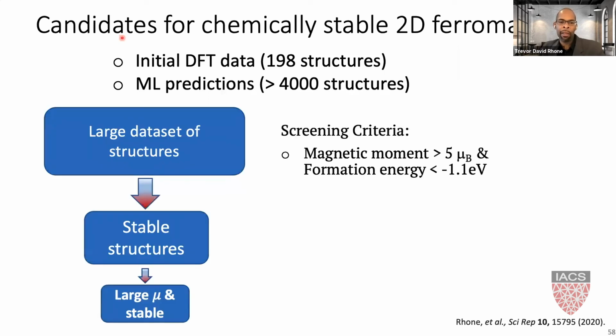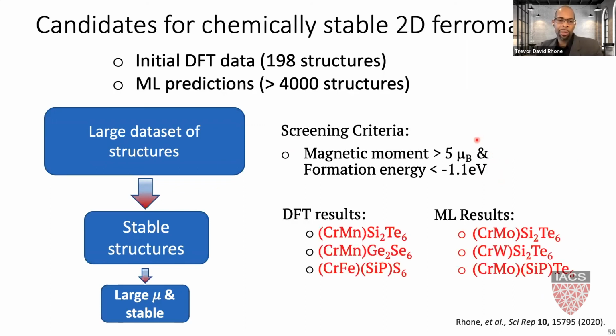I picked those that have a large magnetic moment, and I picked this number, 5 Bohr magnetons, which means its magnetization is large compared to chromium germanium telluride, and also has a chemical stability better than that of chromium germanium telluride. And if you sift through our DFT results and machine learning predictions, which were then verified by DFT, we have a set of structures which are candidates to have large magnetic moment and to be more chemically stable than chromium germanium telluride. So this is already a huge success, but you may be skeptical.